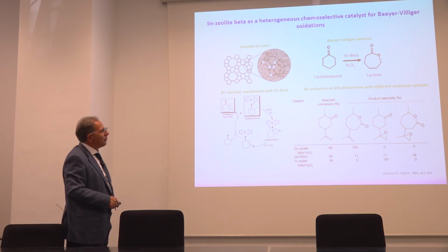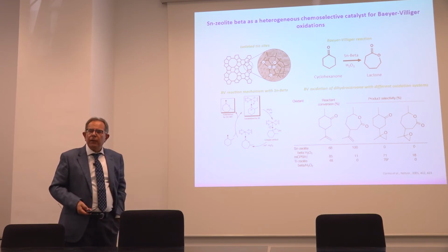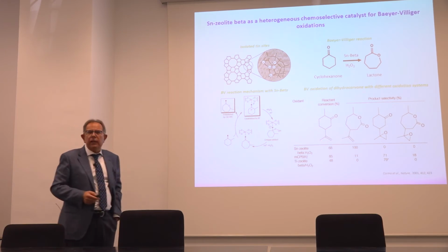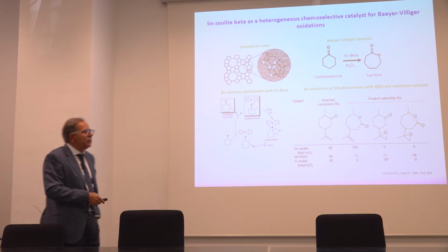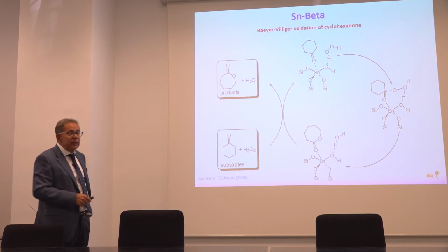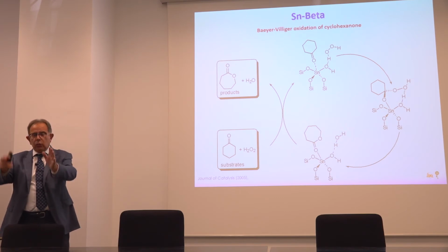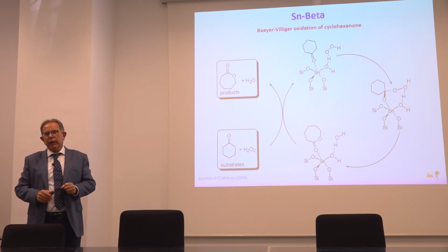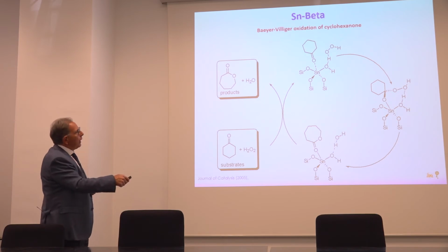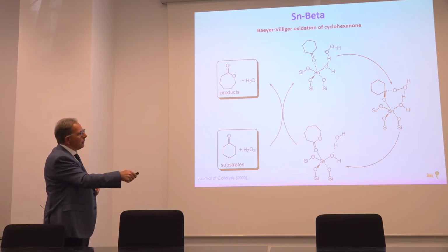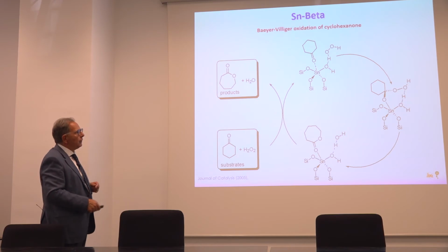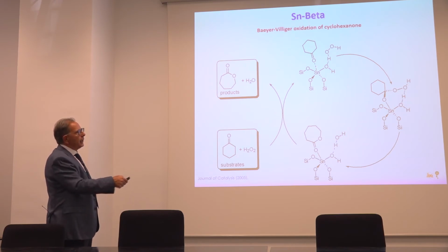Okay, so now what we would like to know is if the real active site was the tetrahedrally coordinated tin, as you put here, or how we had to have that tin for carrying on the reaction. Well, what we did is use tetra-coordinated tin to do molecular modeling, theoretical calculations, and we saw that the reaction was not working. However, when you hydrolyze one of the tin-oxygen-silica bonds, and you generate now one tin-OH, now yes, the reaction proceeds very well. The tin, as we saw, polarizes the carbonyl.